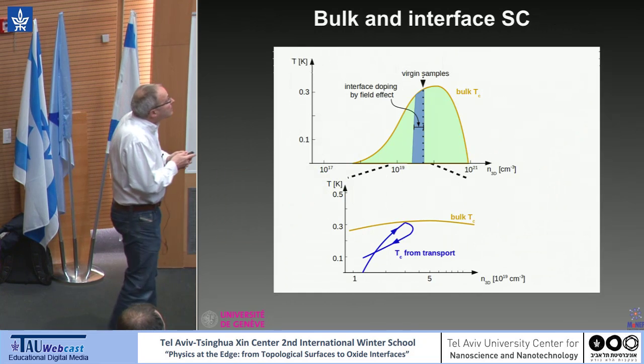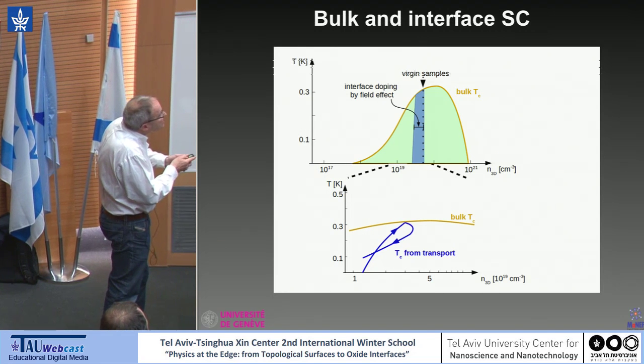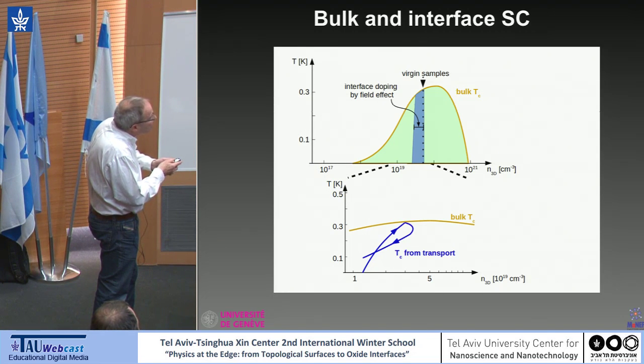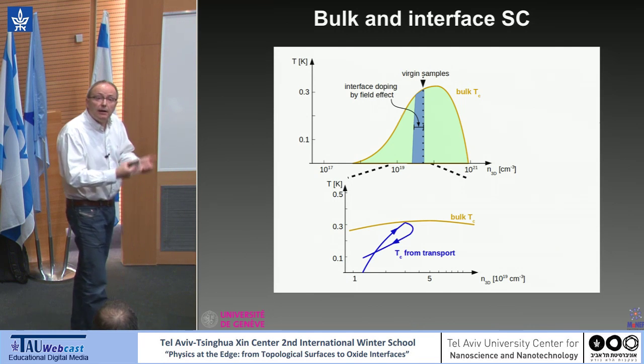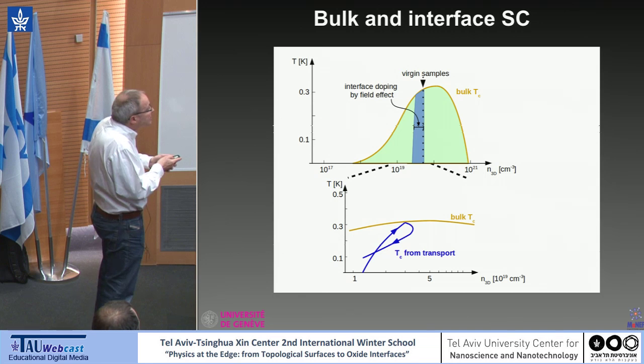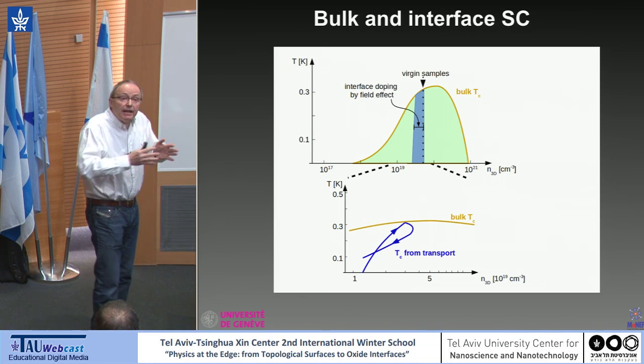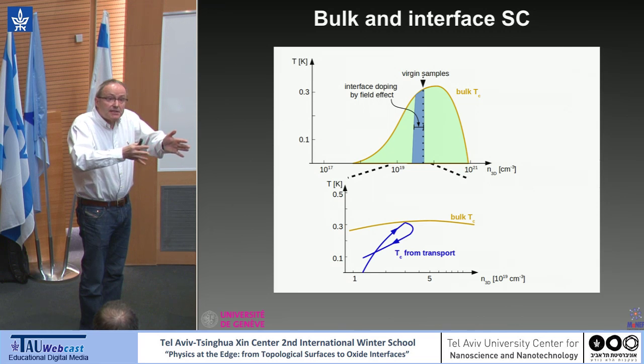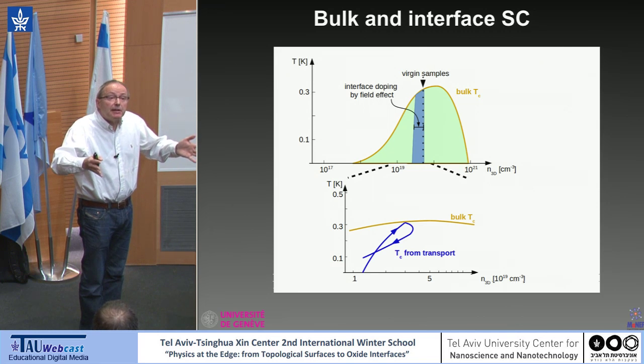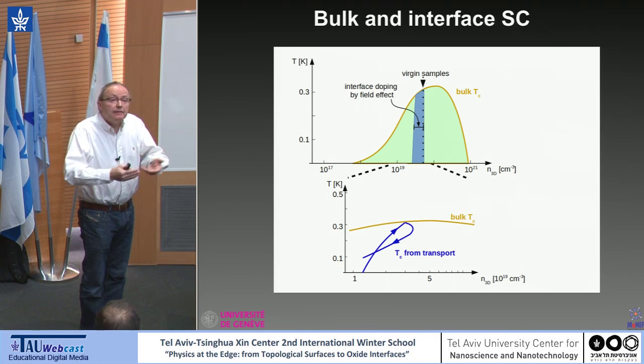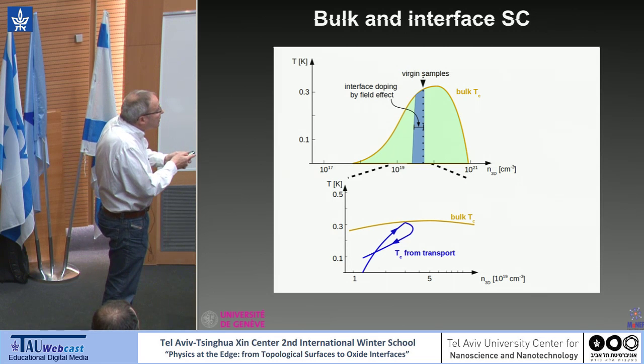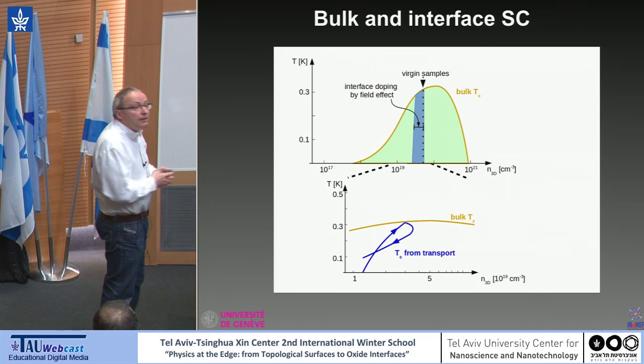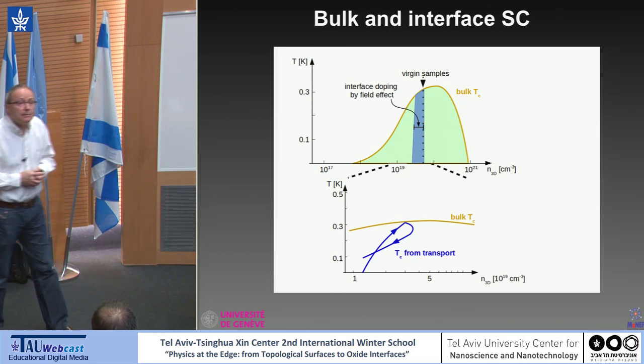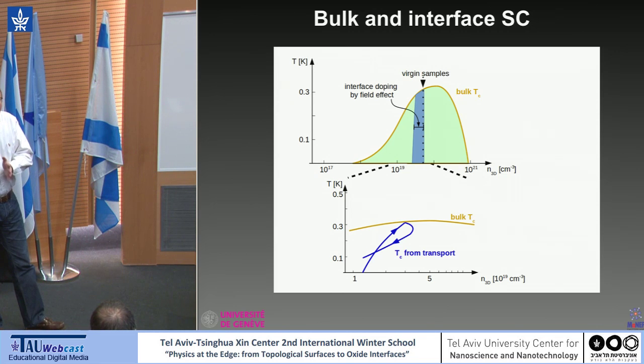Okay, so what I do here, I zoom on this part of the phase diagram. This is the bulk TC, and we start from here, and we start adding carriers. So the thickness is constant. You add carriers, you reach maximum TC, you go a little bit beyond, and then the conducting layer is expanding, and is in fact expanding faster than the number of carriers you add. And so finally you do a loop in the 3D phase diagram. So is this the reason why TC is going down?